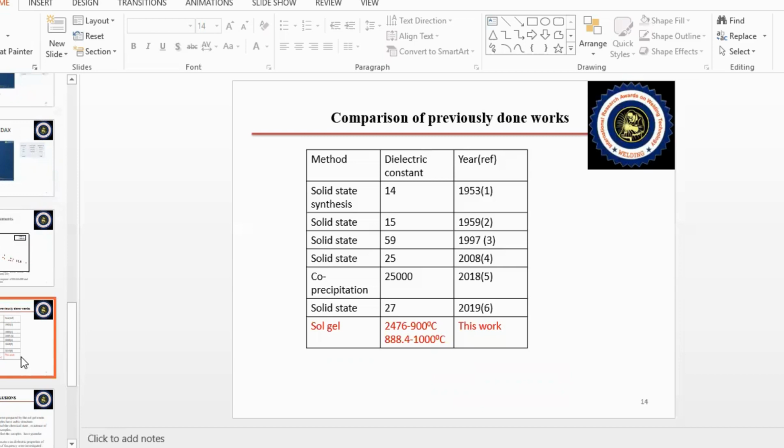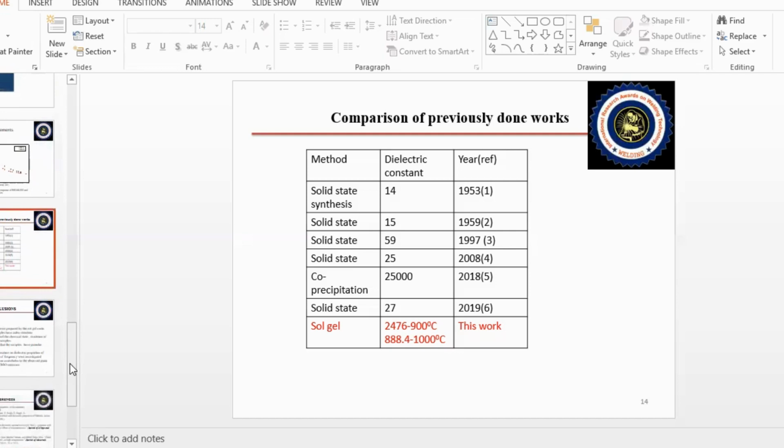The Maxwell-Wagner polarization effect occurs in ceramic materials comprising semiconducting or conducting grains separated by highly insulating grain boundaries. This will lead to the formation of asymmetric charge distribution in materials and contributes to the giant relative permittivity in ceramics. However, it is stated in literature that the reasons behind the dielectric anomalies are still under investigation.